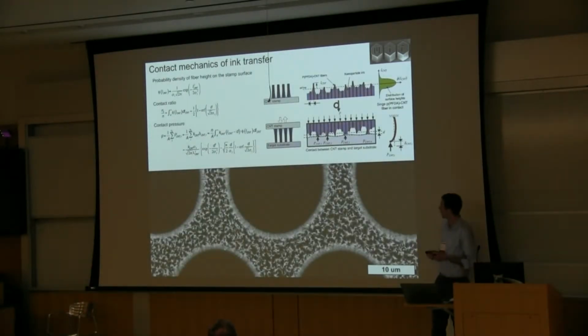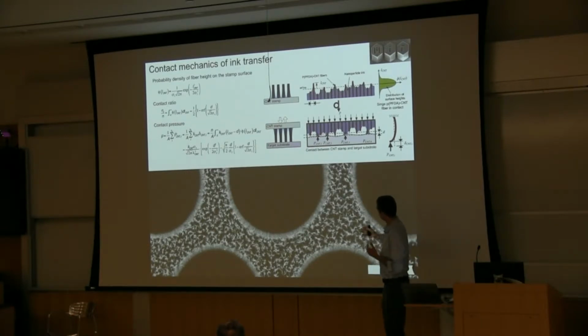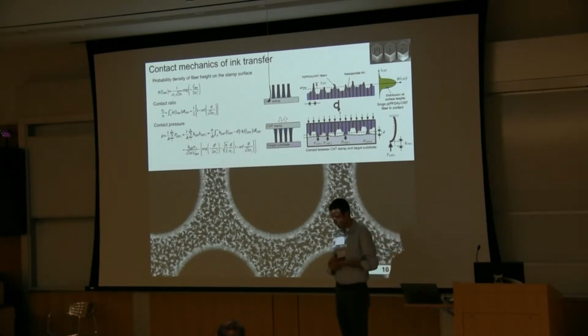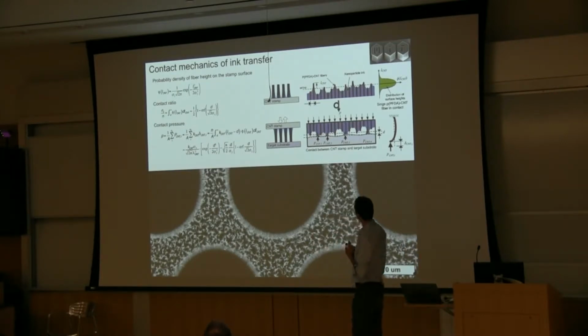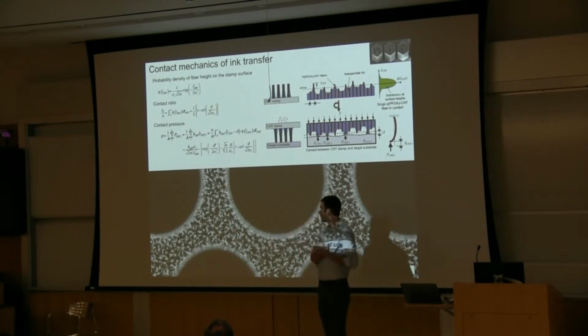We're trying our best to study the real process science behind this, and to first order, we can say that the top surface of the stamp is a distribution of sharp tips, where each tip is 1 or more coated carbon nanotubes with an effective elastic modulus and therefore bending stiffness also based on its diameter. And what you want to do for good printing is press the wet stamp into your opposing surface. So take this and flip it over and press hard enough such that all of the wet nanotubes are in contact. And then you have the opportunity to print a uniform layer.